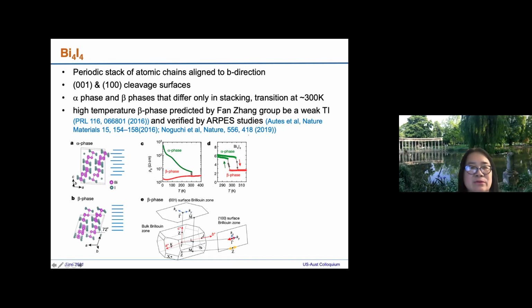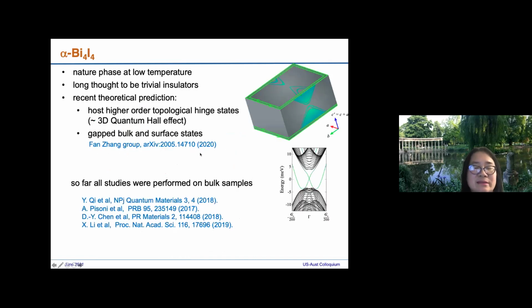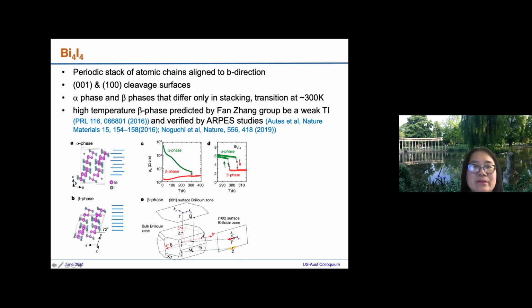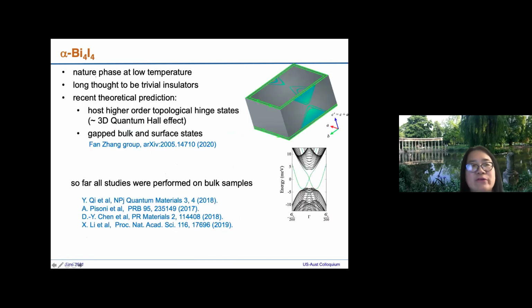This beta phase was predicted to be a topological insulator and has been verified by ARPES studies. So far a lot of the work has focused on the beta phase. More recently there's a theoretical prediction from Fan Zhang's group, who made the original prediction for this material. They think the alpha phase is also quite interesting. It's thought to be a trivial insulator, but it can host higher order topological hinge states, with a gapped bulk and gapped surface states.